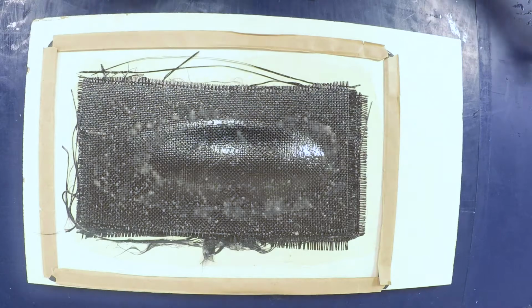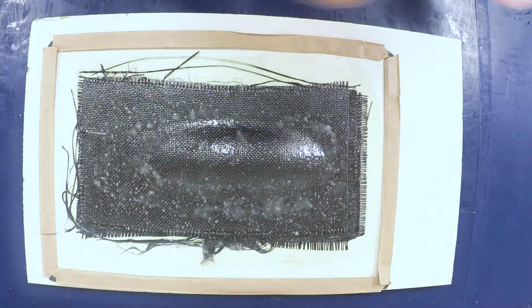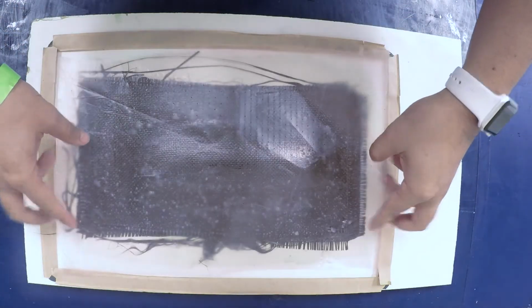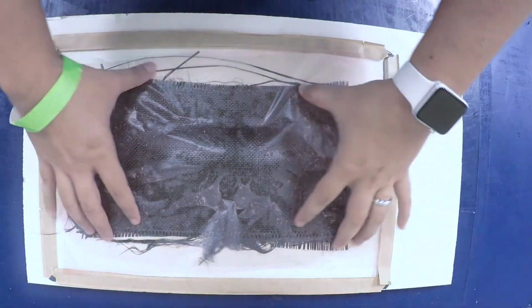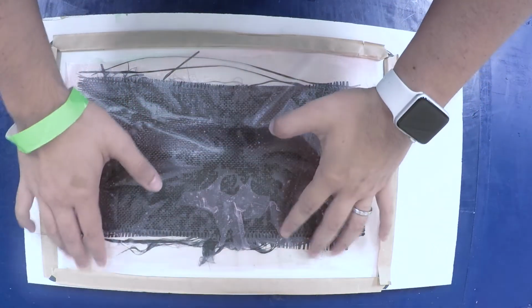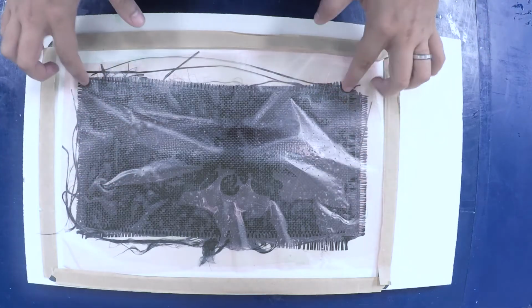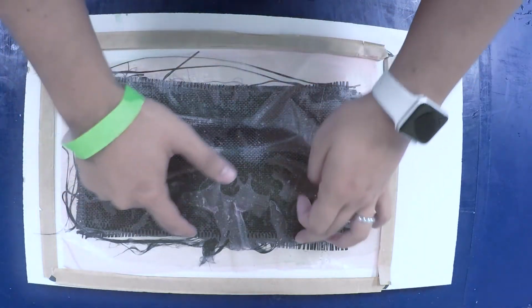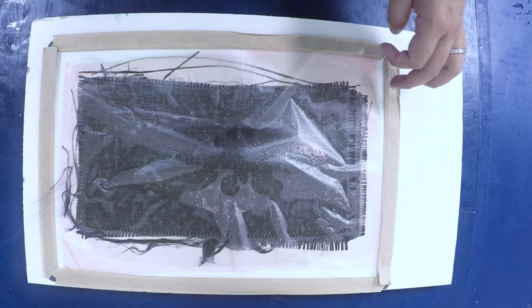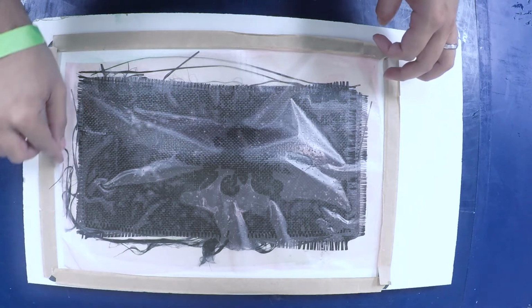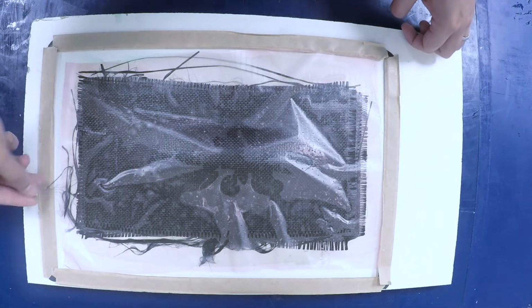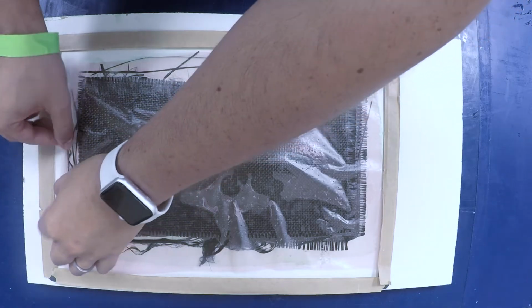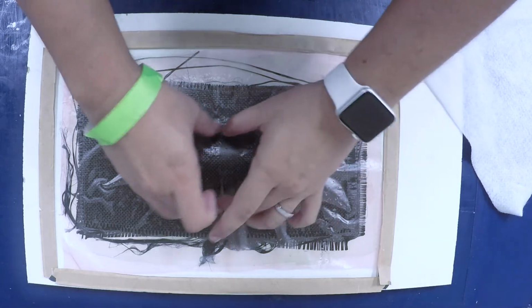Moving back to the layup, we begin by placing the release film down. If necessary, cut any relief cuts into the release film to allow the film to sit flush and as close to the fiber as possible. Any wrinkles in this layer have a high chance of passing on to the final component once this is cured. The film must cover all areas of the epoxy to avoid having the bleeder attaching itself to the final product. Pay close attention to the borders and your tacky tape to ensure that no loose fibers are going to interfere with the vacuum seal.